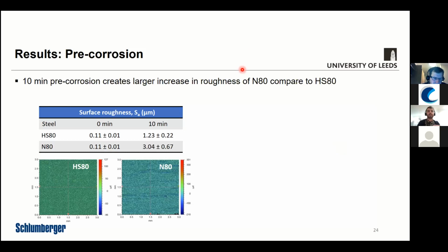So what we did was just complete a 10-minute experiment, expose the steel to the uninhibited hydrochloric acid, take those samples out and do some surface analysis on those. So this is some surface analysis using a white light interferometer. It builds up a 3D scan of the carbon steel coupons after they've been exposed to that environment. And we've got a scale here.